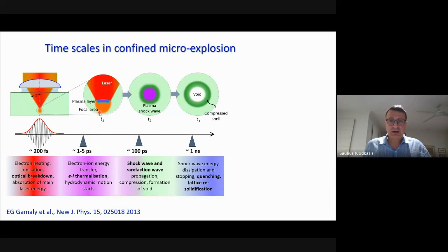All the mechanical effects, all the hydrodynamics, happen later, when energy from the electronic system is coupled to the lattice, to the environment around the modified region. So energy at first is absorbed into the electronic system, and then after a couple of picoseconds, the material starts to be modified. It means also that modification of material is really a kind of pure, so to speak, because the material is not changing during energy deposition. It would not be the case if we were using even just longer picosecond pulses, and nanoseconds obviously even worse. So with femtosecond lasers, you can really make precise energy deposition.